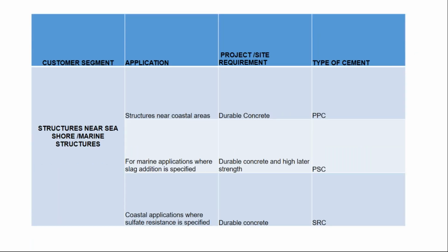Structures near the seashore, marine structures, again need specific attention, especially if both sulfates and chlorides are present, as opposed to areas where sulfates alone are present. We have seen many times that, without testing itself, it is assumed in many places that sulfate alone would be present. So why not go for SRC cement, which can be quite dangerous at times, because SRC cement, as I was mentioning, may not be effective in resisting the attack of chloride.